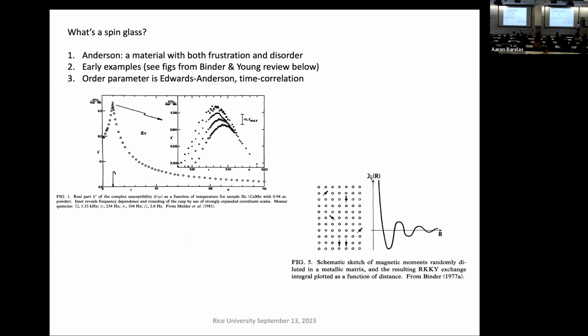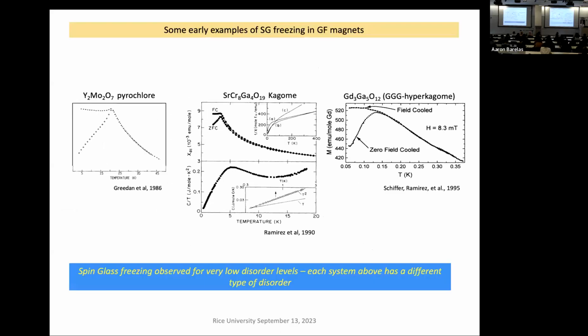So this is really quite astounding, and it fundamentally originates from the nature of how the manganese atoms interact in copper, which is a metal. They interact with the RKKY interaction, which has an oscillatory dependence, and this oscillatory dependence of J on separation between ions, combined with the random positions, is what's thought to be behind the so-called Edwards-Anderson order parameter. Now, here are some early examples of spin glass freezing in geometrically frustrated magnets.